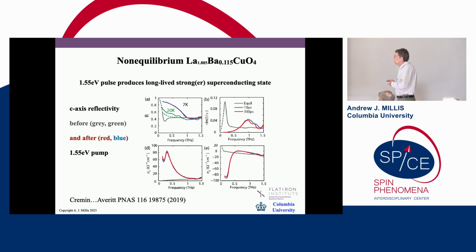They interrogate the system after pumping by looking at the transport in one particular direction, the so-called c-axis direction. And what they want you to see is that in equilibrium, you have a very weak, almost non-detectable superconducting state. That's the gray thing. And after pumping, you get a very long-lived superconducting state. And a signature of the very long-lived superconducting state is that the imaginary part of the conductivity, which is telling you about the reactive response, becomes very large, meaning that there's something which can just slide back and forth without any resistance. So that's the result.